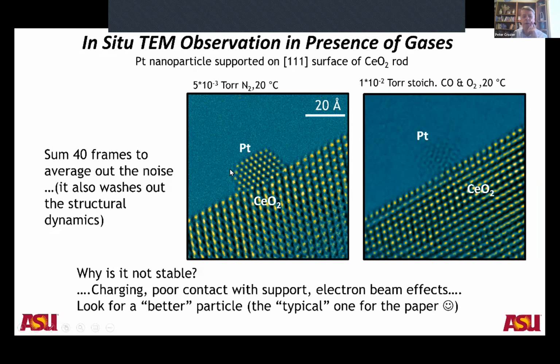But this experiment, which Joshua Vincent did, was very interesting because if we change the reactant gas, the particle becomes stable again. If we pump the CO and oxygen out and go back to vacuum conditions, the particle is stable. Many people that have worked in catalysis for years have speculated that the catalytic functionality is intimately connected to structural reconfiguration of the catalyst, that you can't have reactants being converted to products without some significant structural change in the catalyst. So we were interested in interpreting something like this in a way that might provide hints as to how the catalyst actually functions.